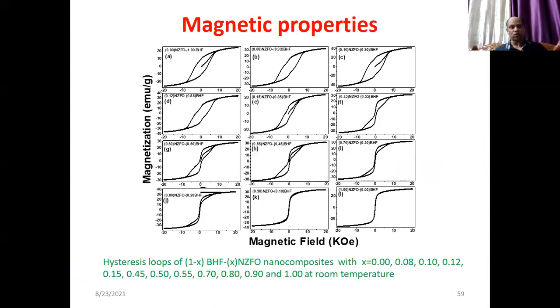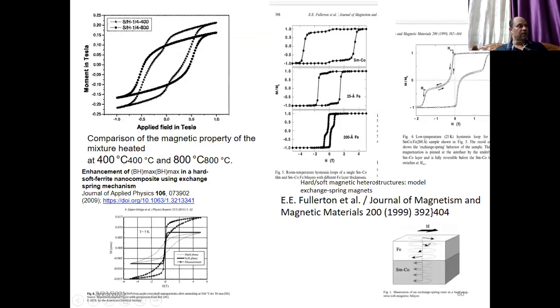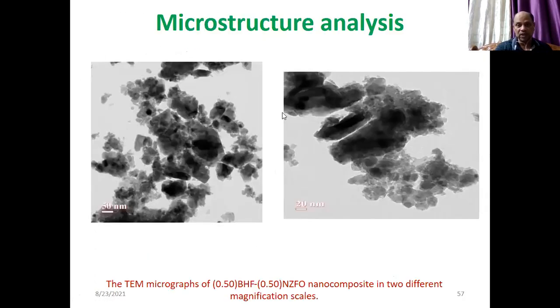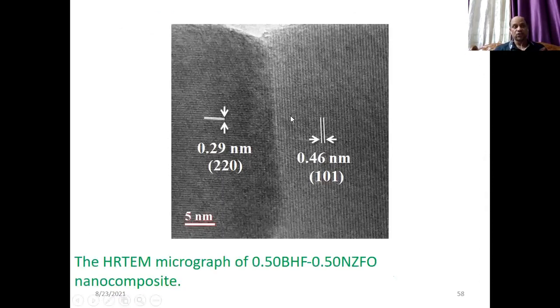You look into that from 0 to 1, nickel zinc ferrite to the VHF. You will find that nickel zinc ferrite is a soft magnetic material, coercivity is 0. Then you go to the VHF and it will be open. You look into that hysteresis loop, it has given a very interesting feature. If you look into the literature also, similar kind of behavior is available, but they say that they are coupling to each other. If you look into this figure, you'll find that they are coupling to each other. So this coupling, and how they are coupling, what I was trying to say, is that people by showing this say that they are coupling each other, so they get a spin distribution function continuous in this surface.